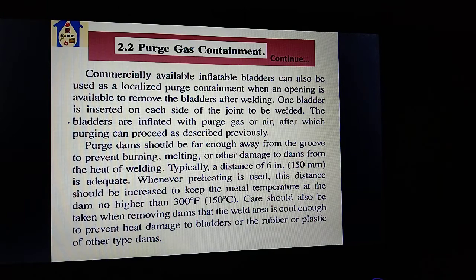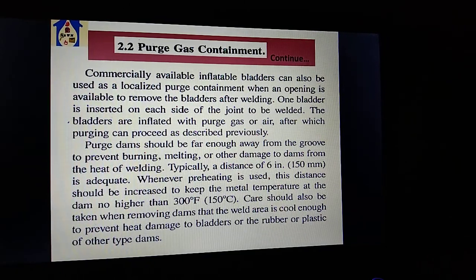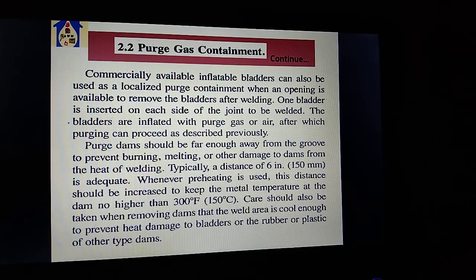Purge dams should be far enough away from the groove to prevent burning, melting, or other damage to the dam from the heat of welding. Typically a distance of 6 inches is adequate. Whenever preheating is used, the distance should be increased to keep the metal temperature at the dam no higher than 300 degrees Fahrenheit, 150 degrees centigrade. Care should also be taken when removing the dam that the area is cool enough to prevent heat damage to the bladder or the rubber or plastic type of dam.